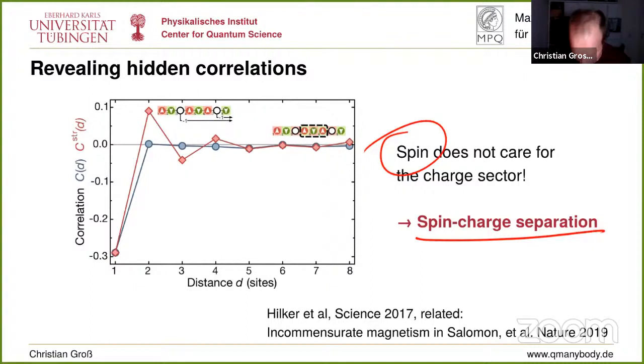What actually is the... so we cool by evaporative cooling, and I think it's in all the microscopes, they do the final cooling now all by a spin mixture, evaporative cooling. It's known that this technique becomes very inefficient around 0.1 TF, because you get a Pauli blocking of the collision channels. That's the problem, which then makes the cooling inefficient.